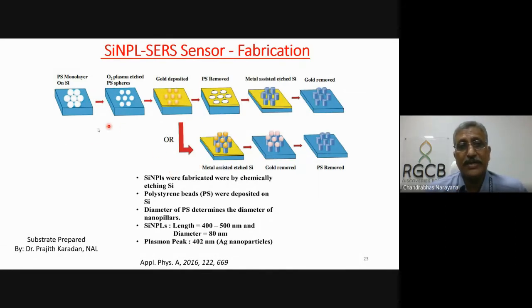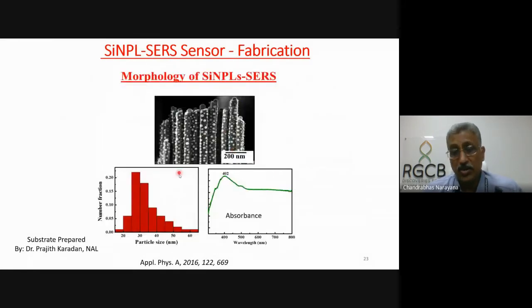So we went ahead and did another experiment where he had got nice nano pillars of silicon by doing etching processes, and it is a metal assisted system. So you can control the size of the nanopillars of the silicon, on which we sputter coated the silver particles. And we can control the size of the silver nanoparticles. But the interesting thing is that the plasmon actually became not localized.